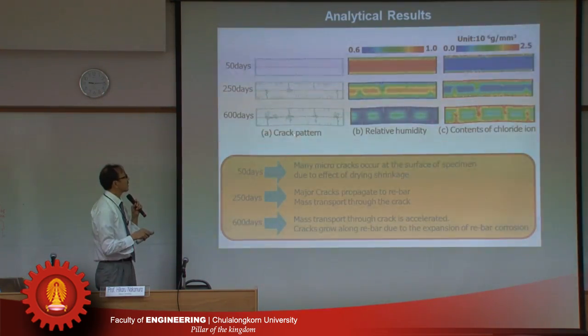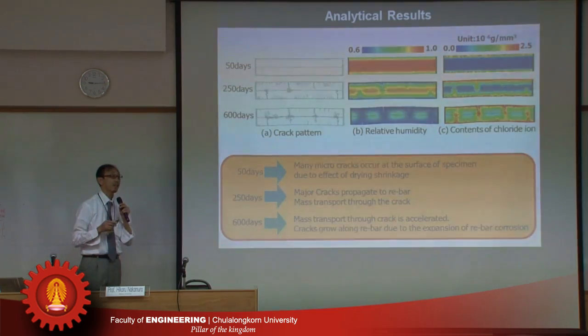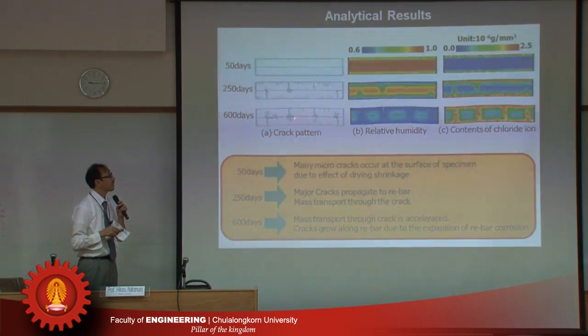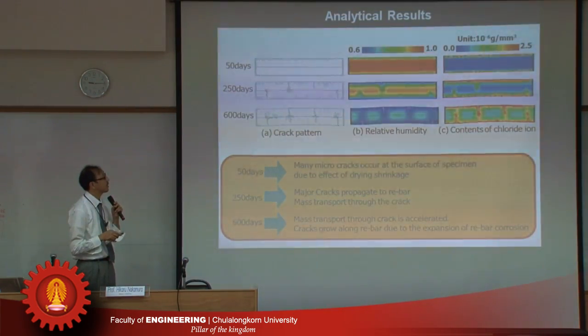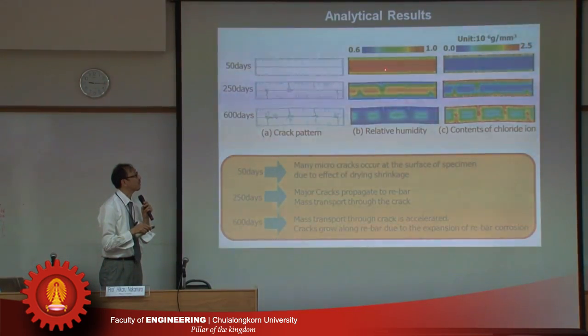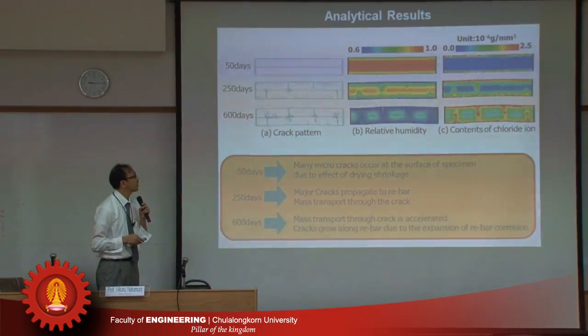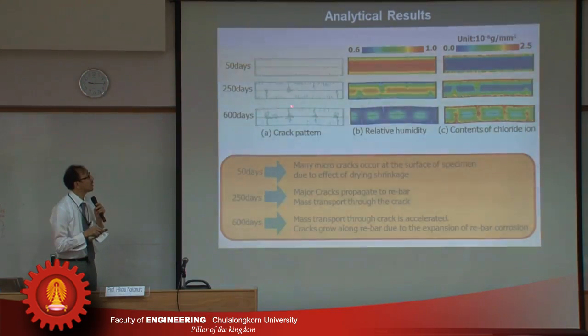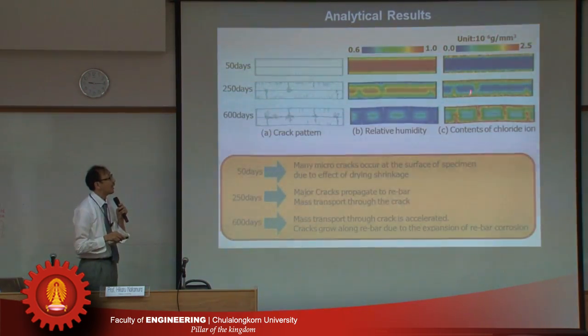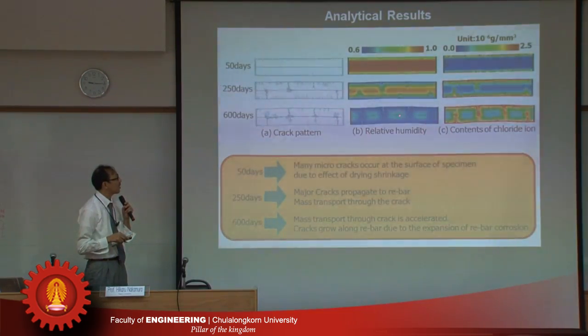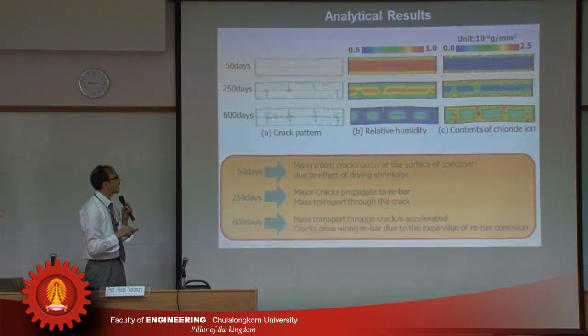So this is the analytical result: crack pattern, relative humidity, and content of chloride ions. At 50 days, this is just a simulation, so the time is not so important. At 50 days, many microcracks occur at the surface of the specimen due to drying shrinkage. Drying occurs from the outside of the specimen, and of course the chloride ion penetrates from the outside. At 250 days, a major crack propagates to the rebar and mass transport goes through the crack due to the higher value. And at 600 days, mass transport through the crack accelerates, and the crack grows along the rebar due to the expansion of rebar corrosion. Because after the corrosion we consider the compatible displacement along the rebar, the crack propagates this way.